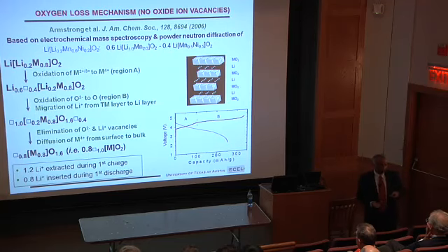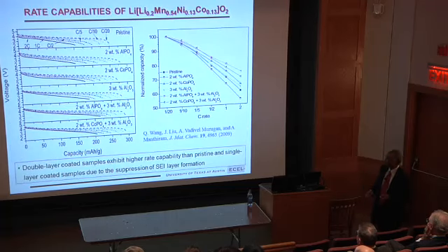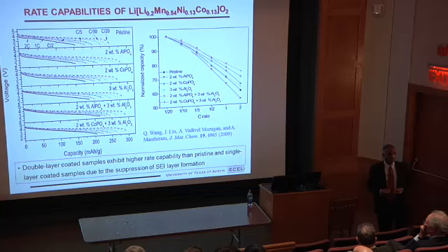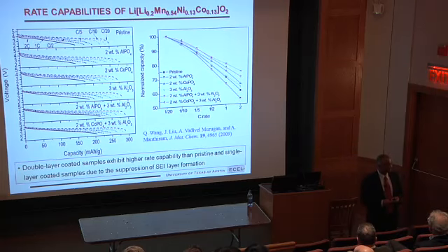On top of it, the surface is very reactive because transition metal ions can oxidize the electrolyte. So if you coat with aluminum phosphate or aluminum oxide, that's much more inert. So the rate capability goes up. It's a surprise. I did not believe it when my students first did the work. What? You are coating with an insulating aluminum oxide, an insulating aluminum phosphate, how come the rate capability goes up?